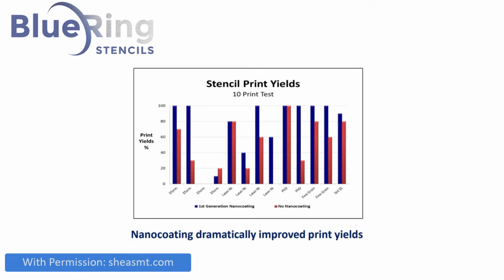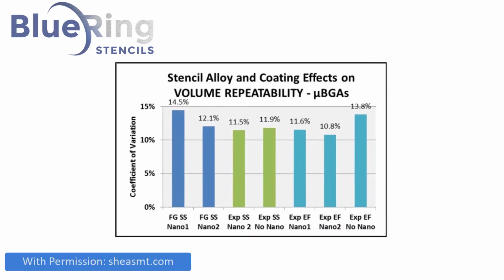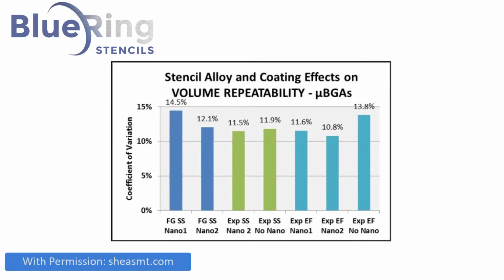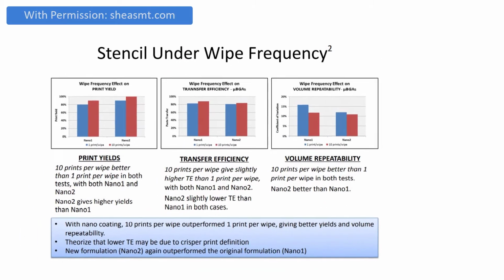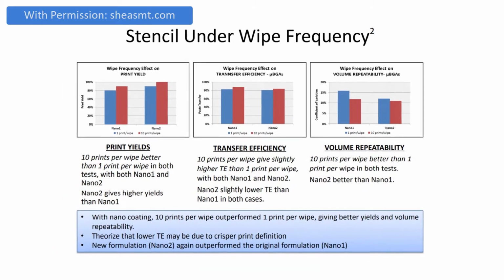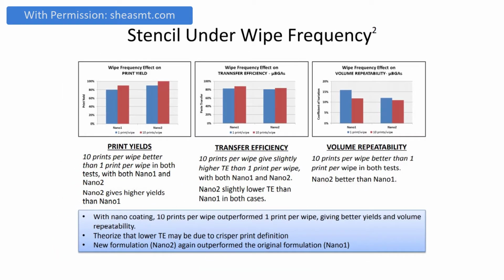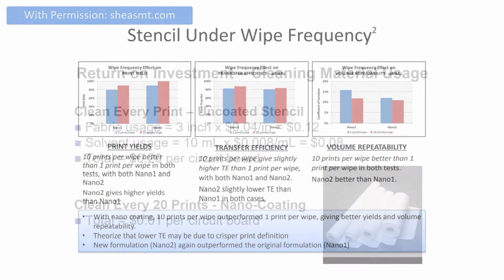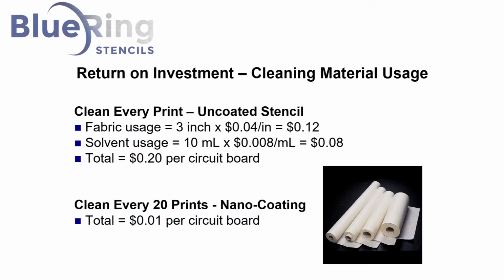Better print definition and decreased underside wipe frequency were the primary benefits of these early stencil treatments and resulted in reduced bridging after print along with lower overall variation in the print process. Customers were able to increase the number of prints between underside wipe cycles from every print to every 10 prints and even every 20 prints. This reduced the use of wiper paper and increased throughput.